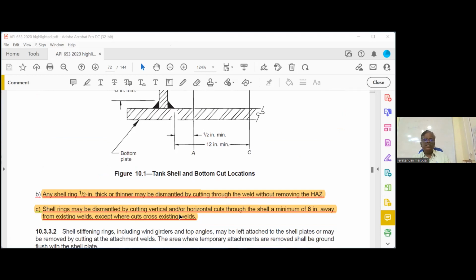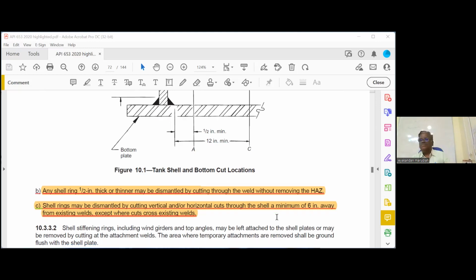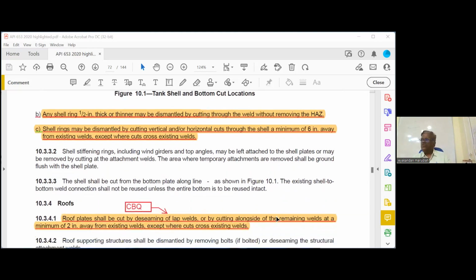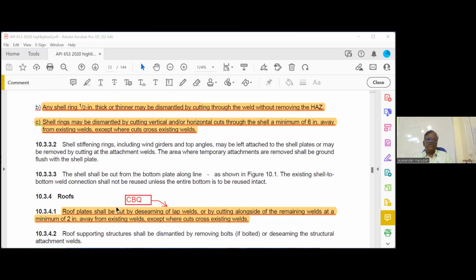Shell rings may be dismantled by cutting vertical and horizontal cuts through the shell minimum 6 inch away from the existing welds, except where cuts cross existing joints. Only you have to cut on the weld or 6 inch away from the weld. That's why I put it very simple. All butt 6 inch is the rule. All fillet 2 inch is the rule. Then roof. Roof also fillet 2 inch only. Highlight this one. Roof plate shall be cut by deseaming the lap welds or by cutting alongside the remaining welds minimum 2 inch away from the welds. So minimum 2 inch away from the welds. That is a closed book question.